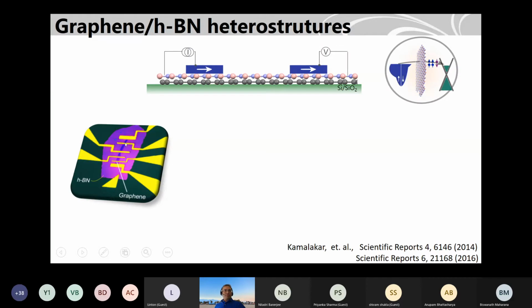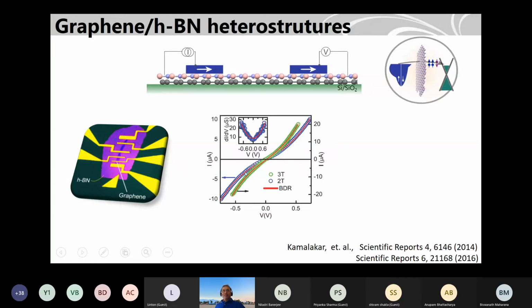And this is, for example, a device with graphene with boron nitride as a tunnel barrier. So this is a single layer. It has some patches, I will come back to that. But it's mostly monolayer boron nitride, and it's CVD grown. So we transfer it and then we patterned it. So it's not a flake; it's wafer scale.